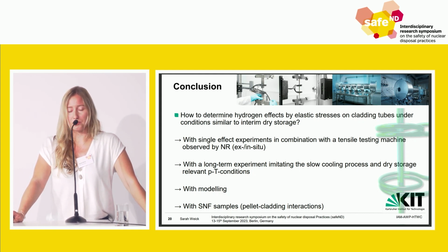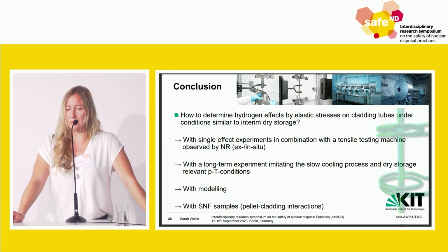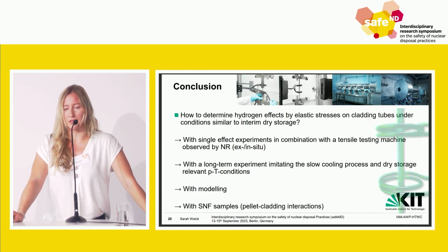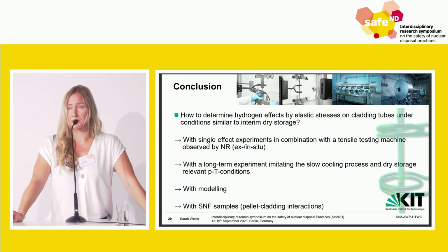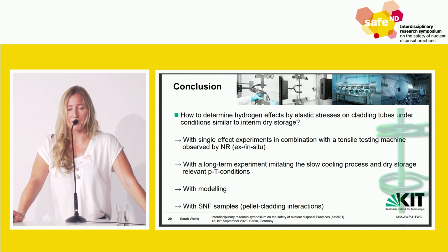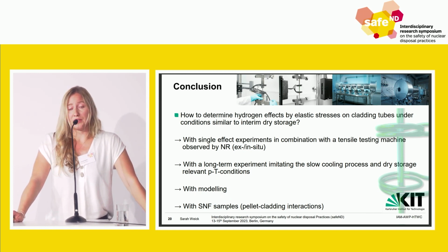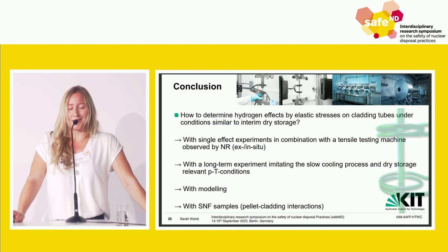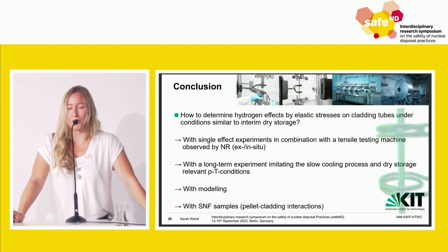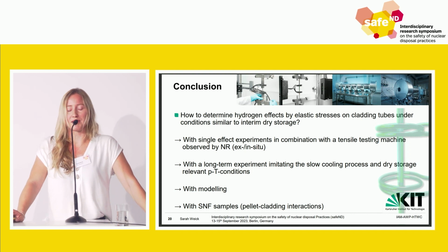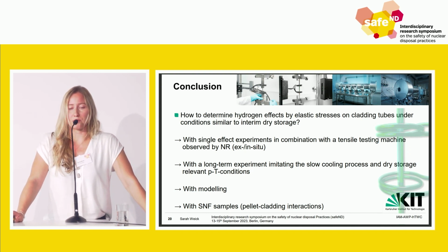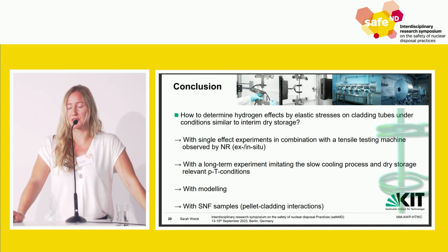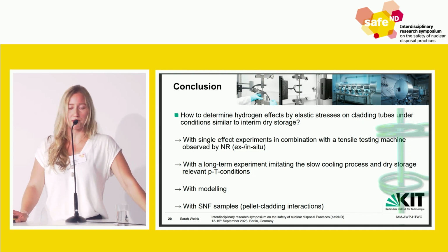Also, we use a long-term experiment that imitates the slow cooling process and dry storage-relevant pressure and temperature conditions, our quench bundle test. Also, definitely, what is mostly done is modeling, which is in fact one of the reasons why we do these long-term and single effect experiments, to gain parameters that are then used for the modeling process.